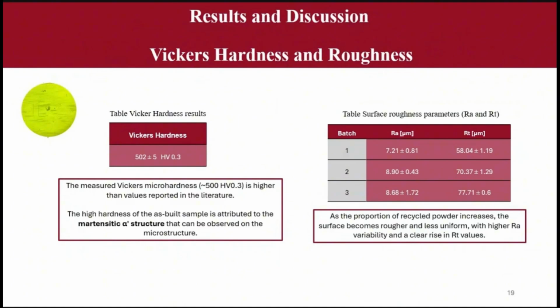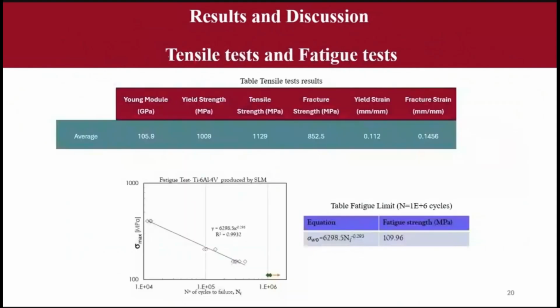For the surface roughness, we found an increase of Ra and Rt with the recycled powders. As I said, below the table, as the proportion of recycled powder increases, the surface became rougher and less uniform, with higher Ra variability and a clear rise of Rt values. Here we present the tensile test results and fatigue limit for a number of cycles. The criterion was a million cycles, as I said. And you can notice that the fatigue limit was about 110 megapascal.